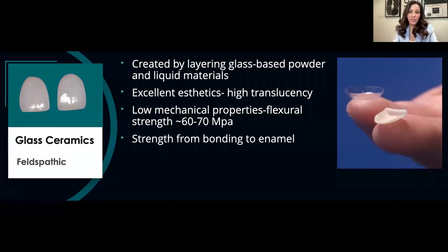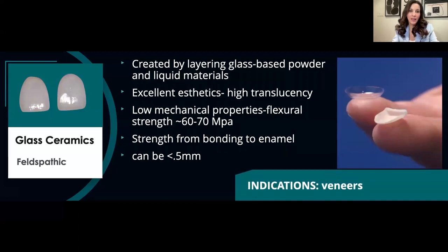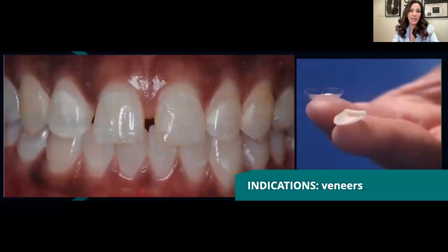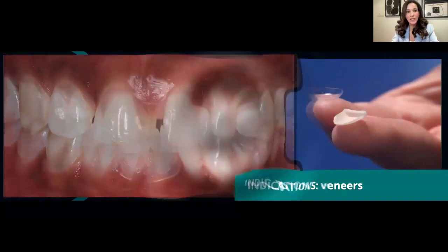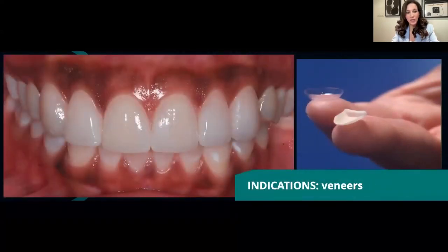And so this material could be made extremely thin, less than 0.5 millimeters in thickness, but its indication is really only for veneers. And with that, only specific veneers, veneers that have enough enamel to bond onto. So not a lot of unsupported porcelain. And so this is an example of a situation where you can close diastemas with veneer material using feldspathic porcelain.